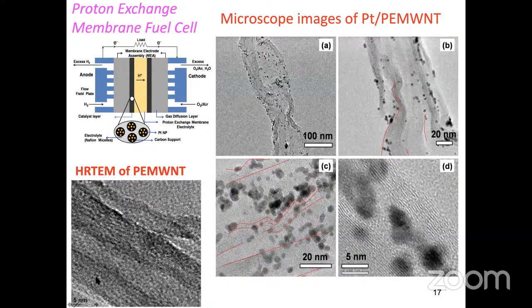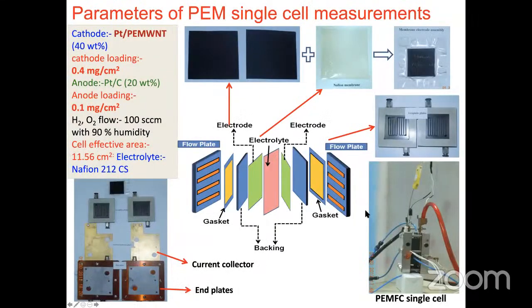And here the carbon nanotubes and graphene. So if you go to each platinum nanoparticle, this will be approximately 5 nanometer. You can see the atomic planes of the platinum. So platinum nanoparticles are crystalline in nature. And once you have done that, what we can do is make the membrane electrode assembly.